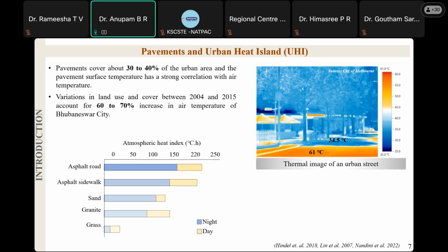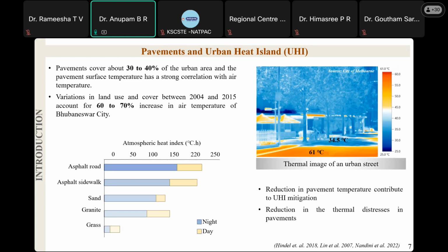If you see the thermal image of an urban street, it reaches up to 61 degrees Celsius, meaning the temperature of the asphalt pavement surface can reach up to 61 degrees Celsius. And this hot asphalt pavement heats the surrounding air also, which is one cause that leads to the urban heat island effect.